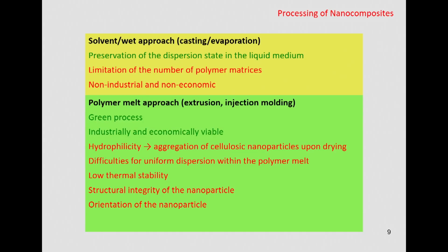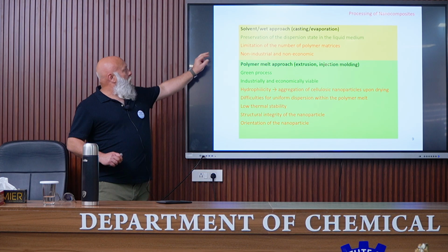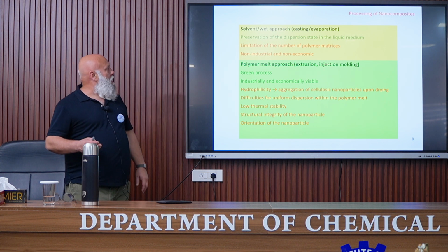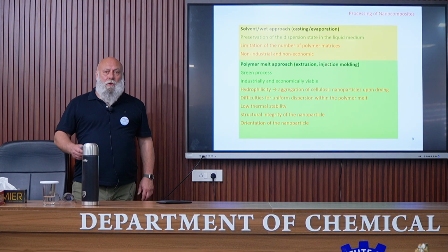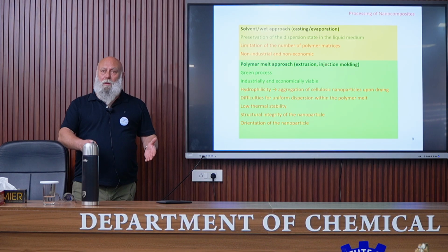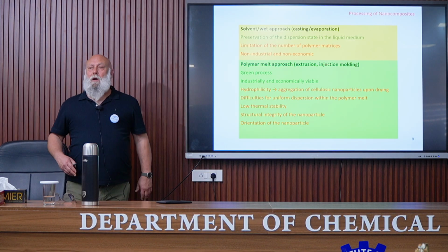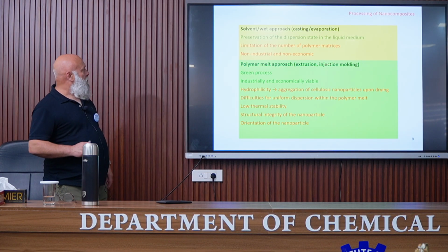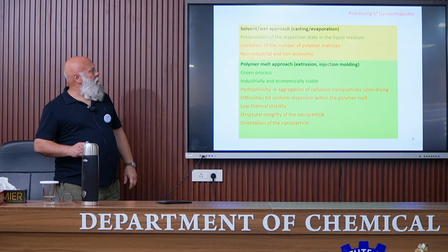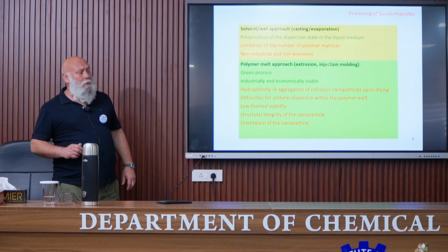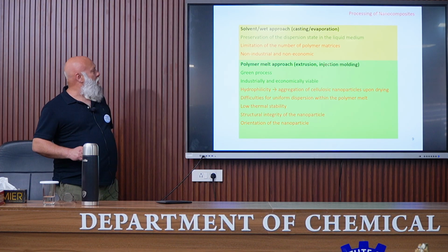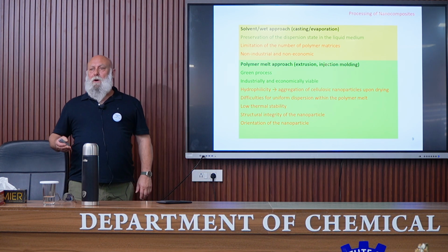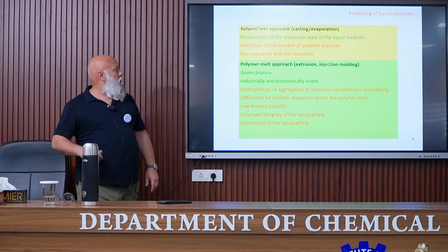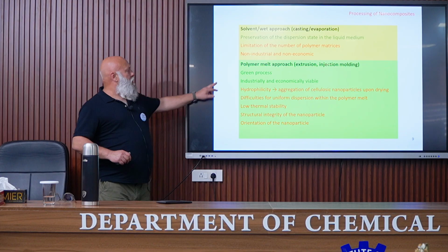Now, a comparison between the wet approach that we've seen previously and the polymer melt approach. I report here the advantages and the drawbacks. For the wet approach, the main advantage is that we can preserve the dispersion state of the nanoparticles in the liquid medium, water, but also other liquid media by different means, by using a surfactant, chemical modification, and so on. The problem is that, of course, there is a limitation in the number of polymer matrices that can be used. And another thing is that this process is non-industrial and non-economic because it generally involves casting evaporation, which is a long process. In the case of polymer melt, it's a green process.